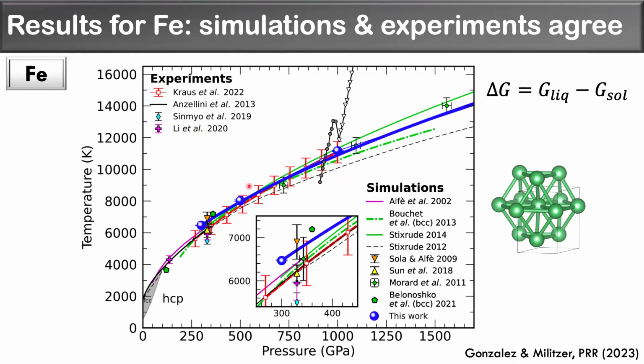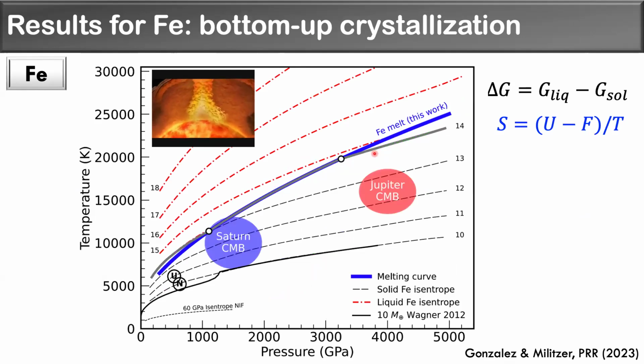And the first thing that this shows you is the predictive power of our simulations. Without having any access to the experiment and doing it completely independently, we're predicting the same measurements that they did in the laboratory, even at these extreme conditions. But since I can crank the pressure as much as I want, I can go to even higher pressures. And that's how I was able to get to 5,000 gigapascals and extend this melting line to regions that have not been explored before. So in addition to the melting line, since we're calculating these Gibbs free energies, which contain entropy, I can also calculate that. And since I have the entropy at different pressure and temperature conditions, I can calculate planetary adiabats, which are lines of constant entropy that you see here in red.